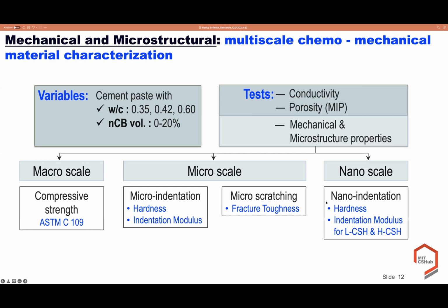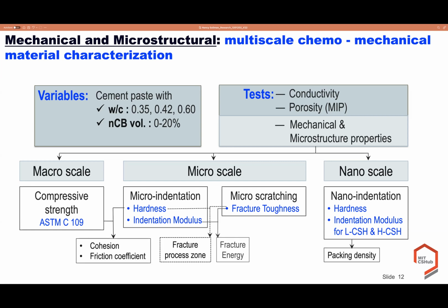Moving to the nanoscale, we measure the hardness and indentation modulus for low density CSH and high density CSH, the main constituents of the bonding agent in the cement matrix. From the relation between hardness and the compressive strength, we can estimate the cohesion and the friction coefficient, the two parameters that define the strength of the material.